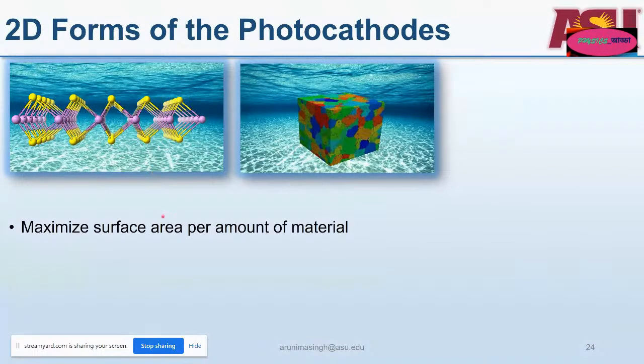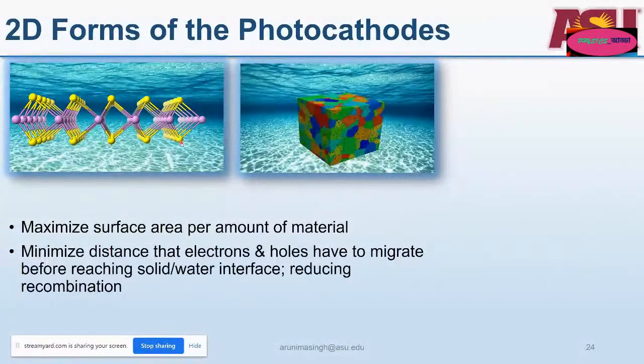The two-dimensional forms actually maximize the surface area per amount of material. So I have more exposed phases per amount of material in comparison to the bulk for a 2D form. That means I have more reactive surfaces. And also, if a photogenerated electron and hole need to reach the surface, they have to travel much less in 2D form, as opposed to bulk, where they have to navigate through grain boundaries and defects before reaching the surface, which can lead to their recombination and loss of energy through that process. So these two intrinsic advantages make 2D materials particularly lucrative for photocatalysis and photocathodes, for instance.